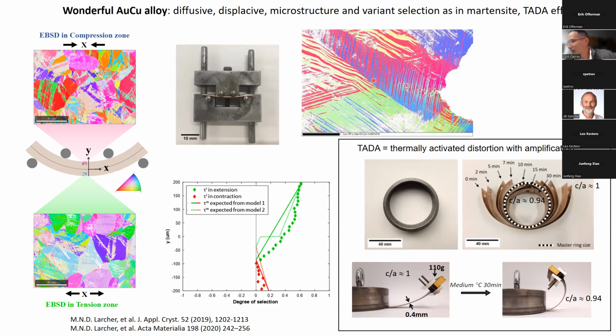And I will finish with that. We also notice a very, very strange effect. We put the thin foil into this ring, we put it in the furnace for 1 minute to initiate the tetragonal transformation, and then we remove the thin foil from this ring. And we have this shape here. It means that we are just at the early beginning of the transformation. The c/a ratio is close to 1.